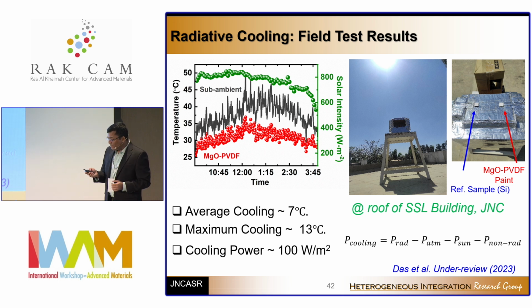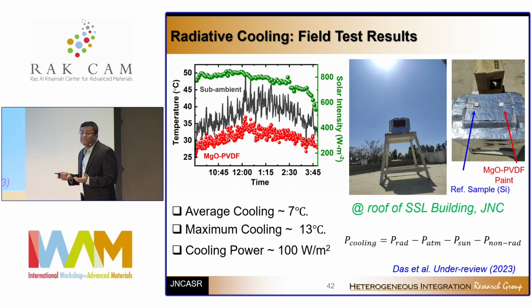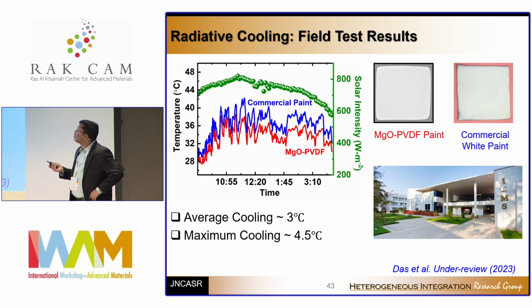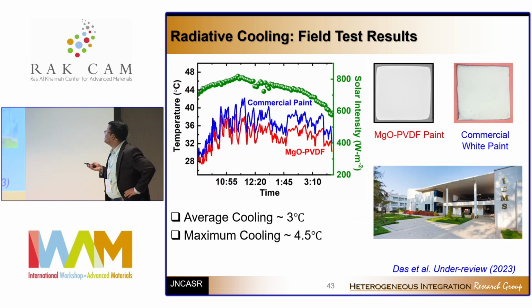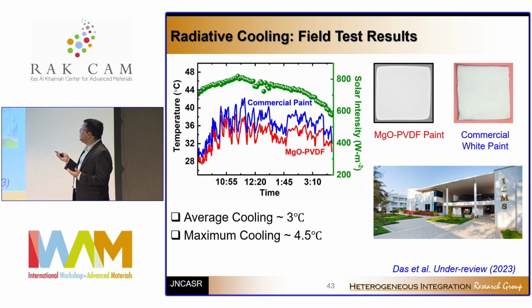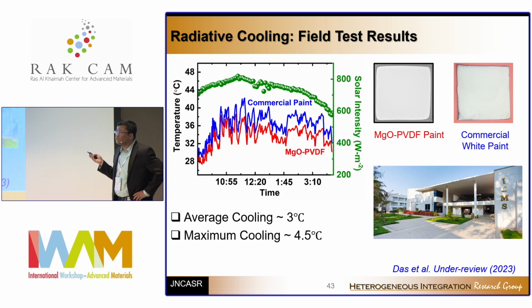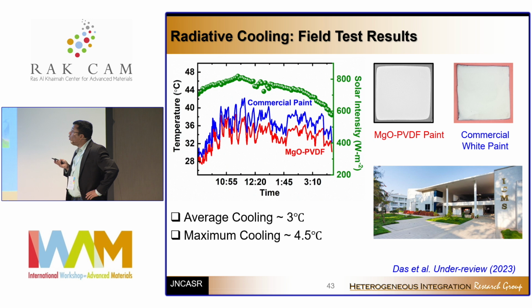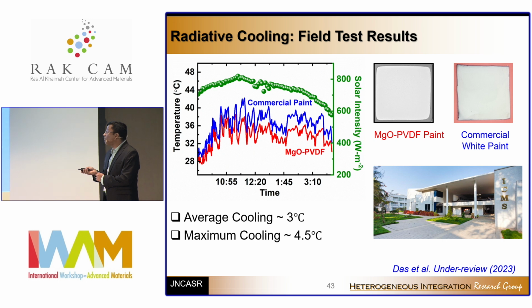So we are very happy, but then immediately the realization set in that there are already commercial paints out there. How does your paint compare with those commercial paints? Many of the buildings in JNCASR actually have white paints. We went to the civil department and asked for this paint, and we used our paint and compared it with this commercial paint. With respect to the commercial paint also, you see our paint cools on average by 3 degrees C and a maximum cooling of around 5 degrees C.